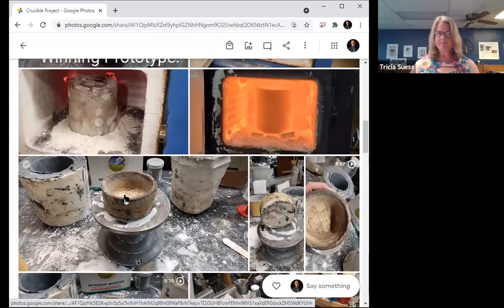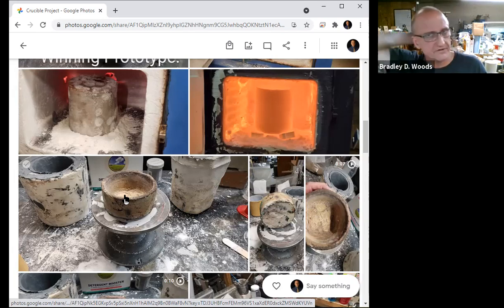Yep. And what happens when it comes out of that first fire? Right. Okay, so when it goes into the first fire, it's highly porous, and it's just particles of silica, alumina, and glass in our recipe. During the first firing, which is the bisque firing, the reason it shrinks by 25% is that it's densifying. So we go from a highly porous object to a nearly solid object during the firing process.